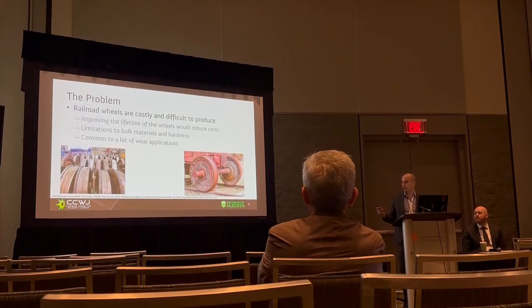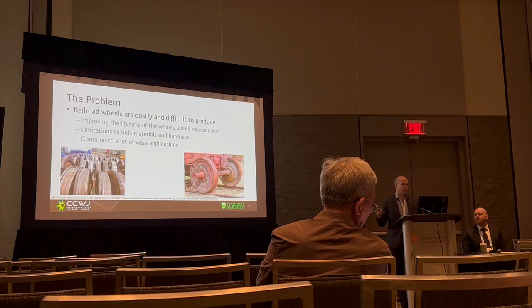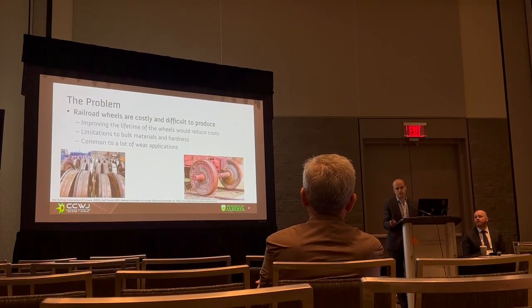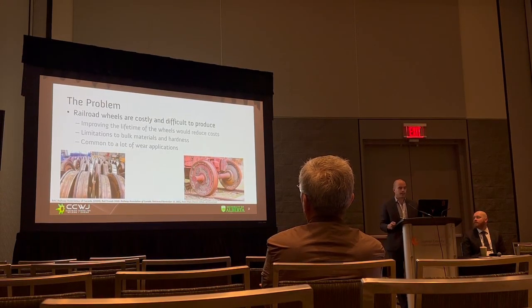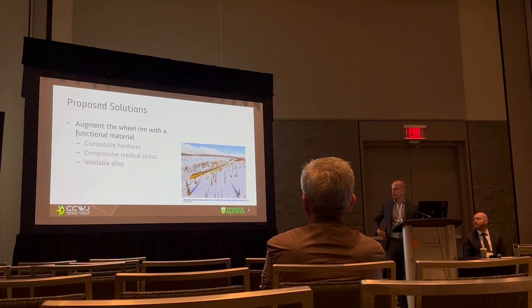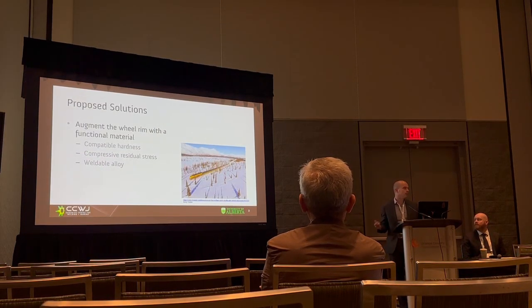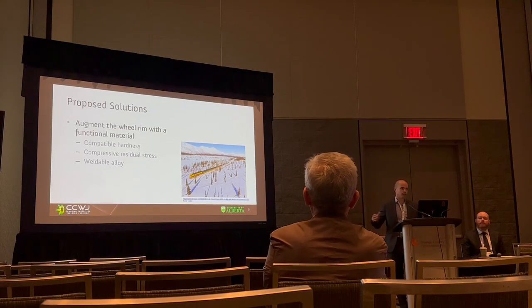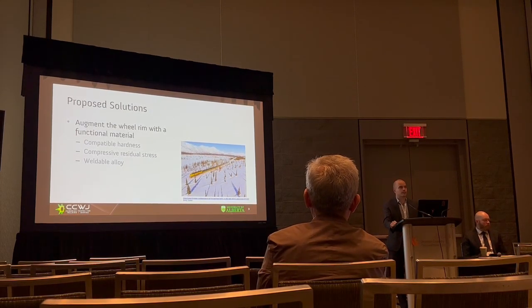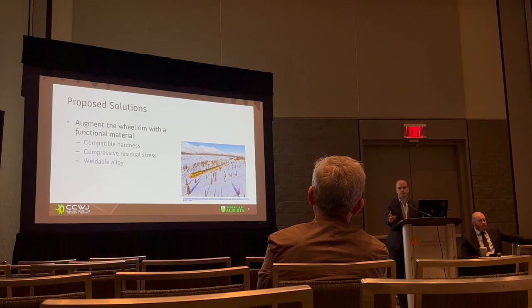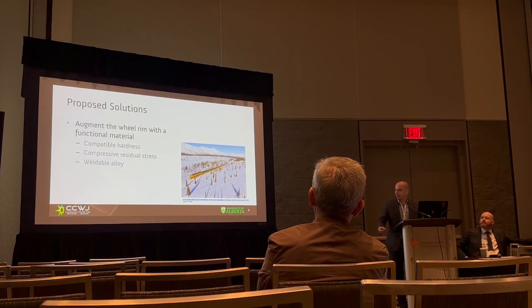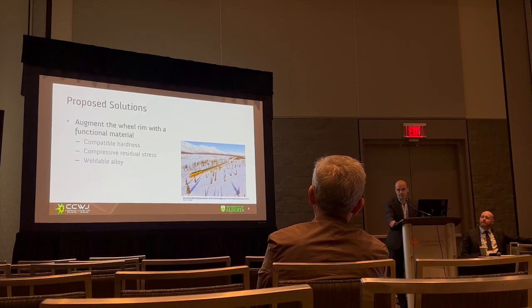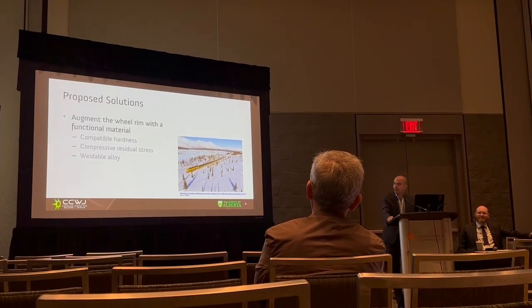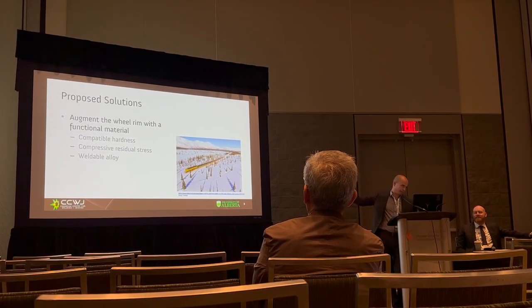There's been interest in trying to do what seems like an obvious solution to a lot of us, weld something onto that wear surface rather than just casting the part, for years. But that came with its own set of issues, which was that the wheel is intended to fail. So you put tracks out in places like that, all across North America especially, and if I go and hard face this wheel, which a lot of the people I talk to back home in the resource extraction industry are like, oh, you want your wheel to last longer, you throw a tungsten carbide in it, and it'll last forever. Well, but then I've turned my wheels into moving grinding discs, and the poor tracks are gonna be gone in a year, and nobody wants to go out and put new track down out there.